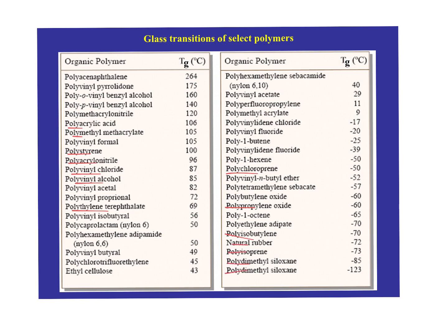All right, so all these things have very different glass transitions. And so just to pick on one, if we go to polystyrene, it's easy to remember. It's got a Tg of 100 degrees, which suggests that polystyrene should be useless to us in pure form, and certainly it is. But as you now know, we toughen the heck out of it with rubber, for one thing, in a variety of different ways. And also we make sure that it's amorphous so that it doesn't have all the crystallinity that makes it even more brittle than just the glassy form would otherwise dictate. And remember, the Tg is part of the amorphous state and Tm is part of the crystalline state.